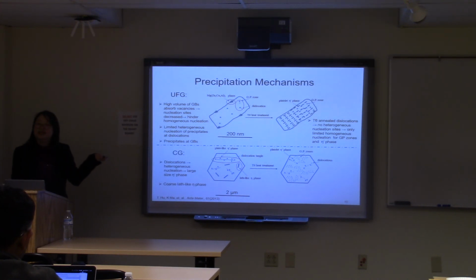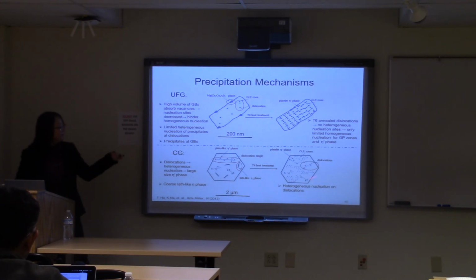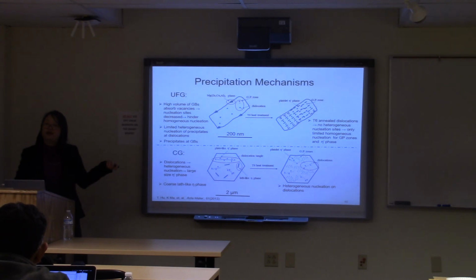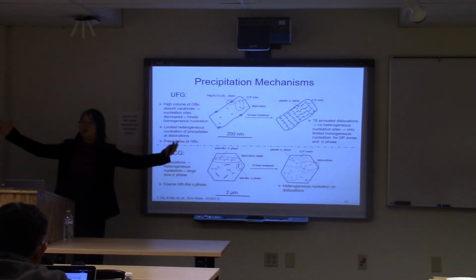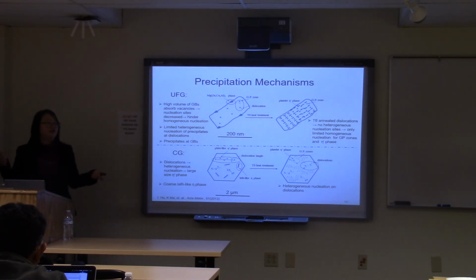Again, this is in the as-extruded condition, so we haven't applied the T6 temper yet to this. And after the T6 temper, although we also have some annihilation of dislocations, because now the grain boundaries are far away from each other, there's still room for you to maintain the dislocations.